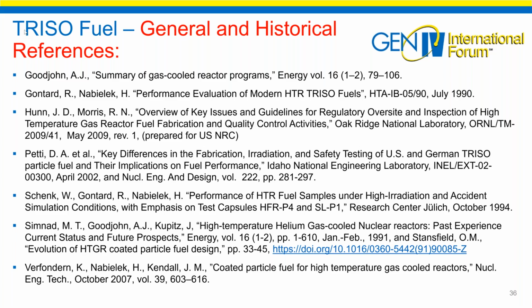and it might be longer depending on how far you vary from the reference design. But we picked the enrichment to be able to handle long-lived cores. We picked the packing fraction to be high. We've actually done studies, and this is public. We've gone up to 40% packing fraction. By the way, the theoretical limit is 66%. I'll let you think about that. If you stack up oranges in a hexagonal, triangular lattice at the maximum per sphere packing, it's 2/3. So you're not going to get 90% packing fraction. I had one person say, oh, I can go 90%. I said, no, you can't. If you have the minimum amount of matrix, it's maximum 2/3. So there are limits on the fuel vendor's variation.